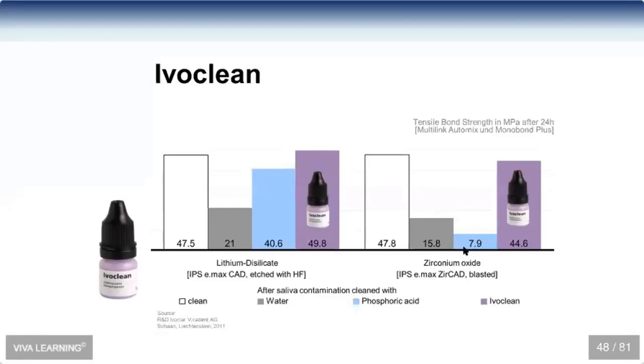And these are the crowns that fell off 3, 4, 5 times, where doctors would call back and say, it keeps falling off. And we'd say, well, clean it again and put 2 coats of the zirconia primer on. Let me know what happens. It fell off again a day later. So the absolute thing we want to do is make sure we don't use phosphoric acid. If you forget, or your assistant says, oops, I used phosphoric acid, the IvoClean will get rid of the phosphates from the phosphoric acid, just like it will from the saliva.